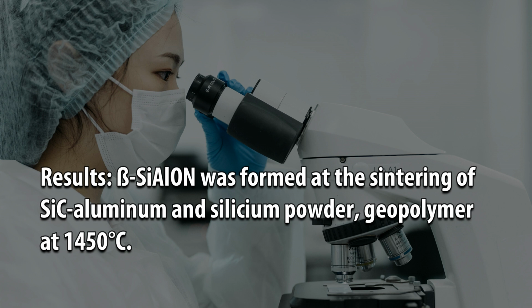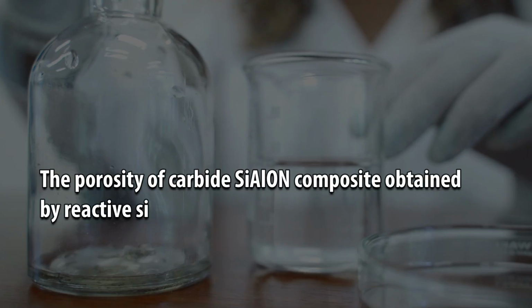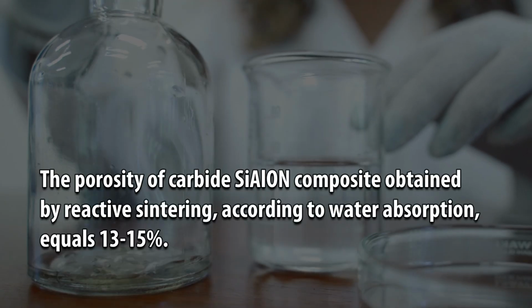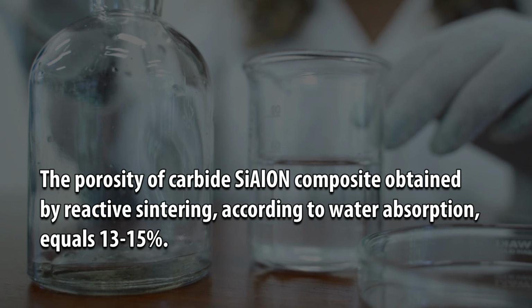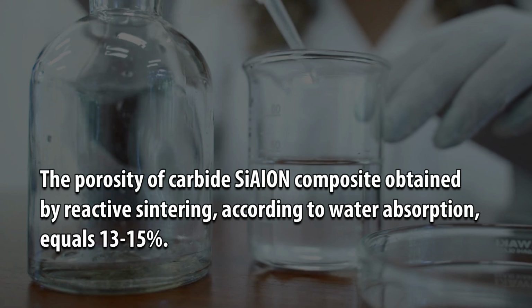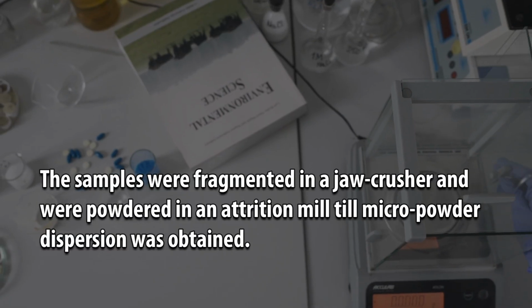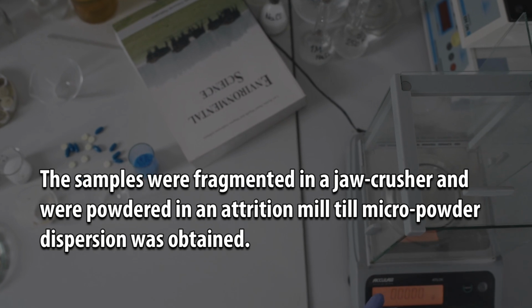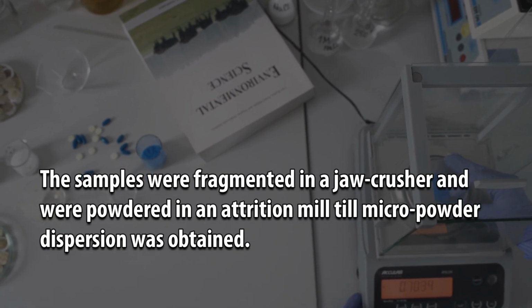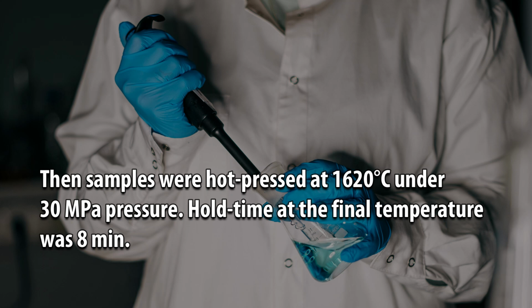Results: beta silicon aluminum oxynitride was formed at the sintering of SiC, aluminum and silicon powder, geopolymer at 1450 degrees Celsius. The porosity of carbide SiAlON composite obtained by reactive sintering, according to water absorption, equals 13 to 15%. The samples were fragmented in a jaw crusher and were powdered in an attrition mill till micropowder dispersion was obtained. Then samples were hot pressed at 1620 degrees Celsius under 30 megapascals pressure.